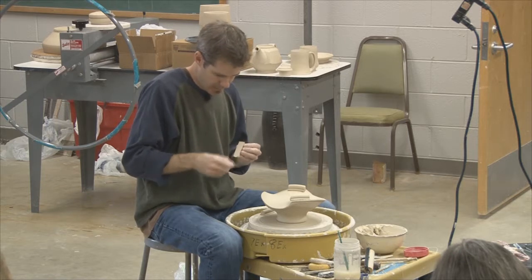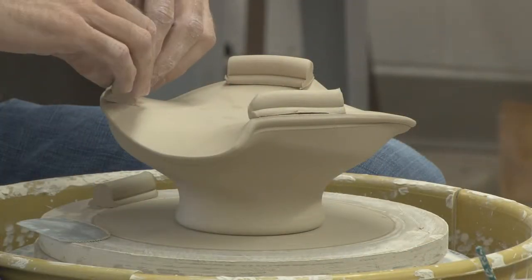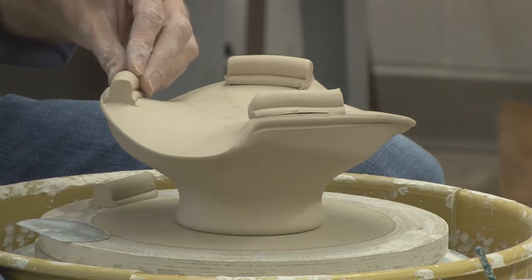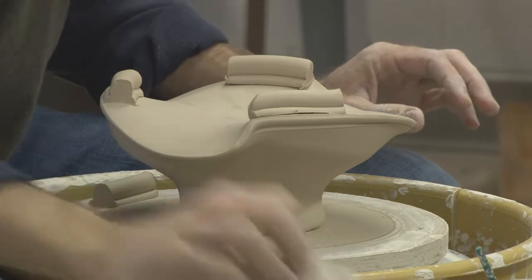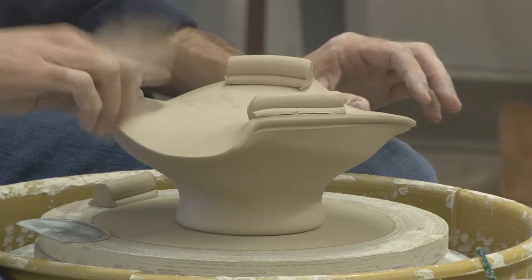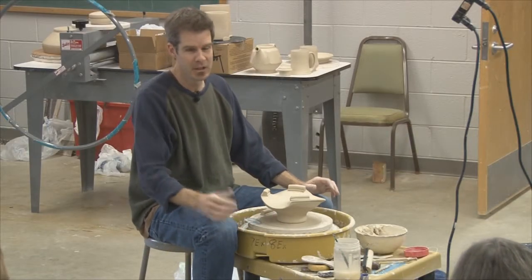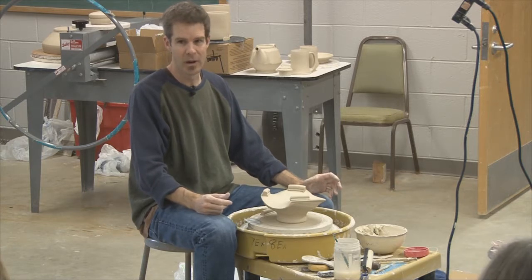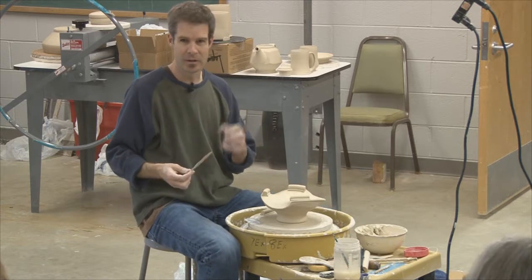When I was first out, I was telling you guys yesterday that a woman, Kathy Adams in Georgia, had let me use her kiln. And at one point I was having problems with parts of my feet sticking to the shelf, and I'd lose a little chunk of my foot. And I couldn't figure out why. I didn't know enough about materials and glazes. She used a lot of Shinos, and the Shinos were probably putting out a little bit of soda ash onto the shelves, and she was just using a silica and EPK kiln wash. And the kiln wash was fluxing a little bit over time, and so things were starting to stick to it slightly.